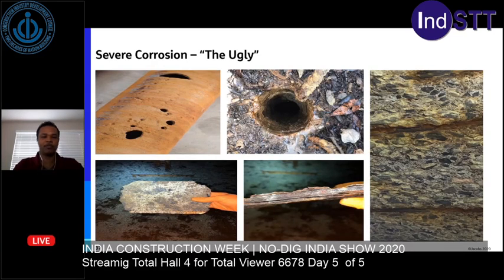And here's a few pictures of the severe corrosion, the ugly corrosion. So the top left, you will see some through wall corrosion that's occurred on a pipeline. The top center, that used to be a carbon steel well. The casing well is no longer there. On the right side, you'll see some rebar corrosion that's occurred from erosion corrosion. And the two pictures with the gloves, that used to be the roof of an above ground storage tank, and it was found to actually land on the tank floor during a tank inspection. Next slide.